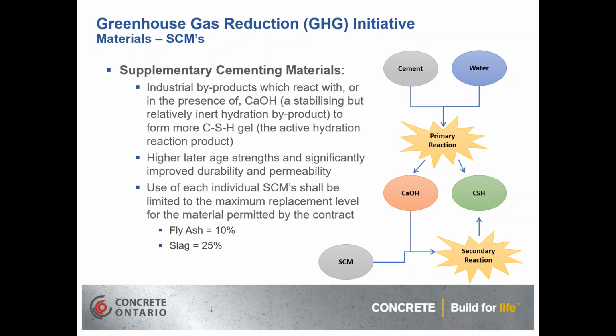But we also have a byproduct produced during that reaction, which is calcium hydroxide, which, although it is stabilizing somewhat, is relatively inert in the sense that it doesn't add a whole lot to the strength or durability of the concrete. And that's just the natural byproduct from it. The supplementary materials will react with that calcium hydroxide, or in the presence of it, with a secondary chemical reaction, and it's going to form more of that calcium silicate hydrate gel.